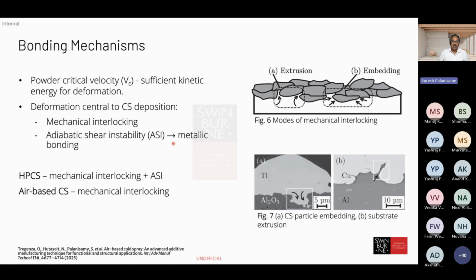So the bonding mechanism also varies based on whether you're using gases, low pressure, or high pressure. That varies quite a lot. As you can see, the modes of mechanical interlocking might change, with extrusion of the substrate happening and also embedding of the particles into the substrate. You can see that in the micrograph here: titanium on top, on the aluminum oxide coating on the bottom substrate. Similarly here, copper on the top and aluminum on the substrate. So you can see the aluminum extruding into the powder particle, and also the embedment of copper on the substrate.